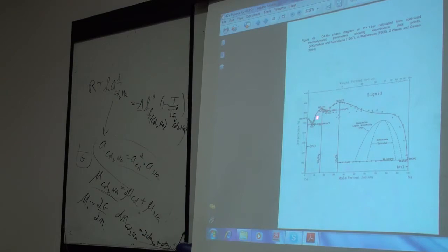And similarly, these liquidus points here permit me to get the heat of fusion of that compound, which I will probably assume is a linear function of temperature, the heat of fusion being constant, unless I really have some CP data. If I have CP data, sometimes I might have CP data for this compound, then I could use that.